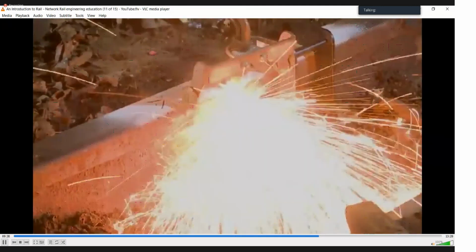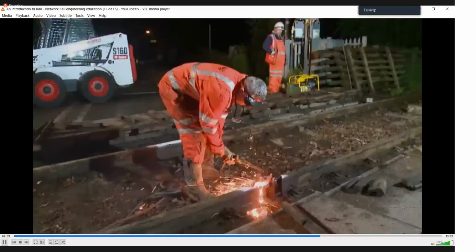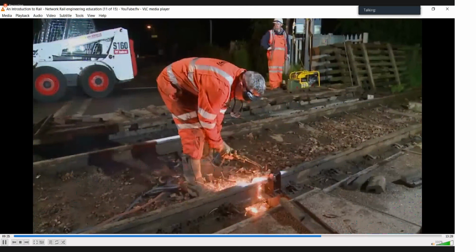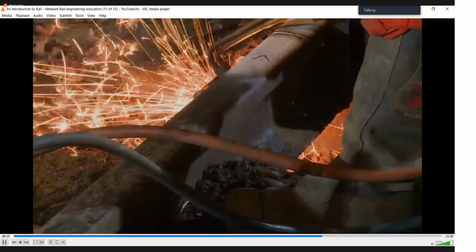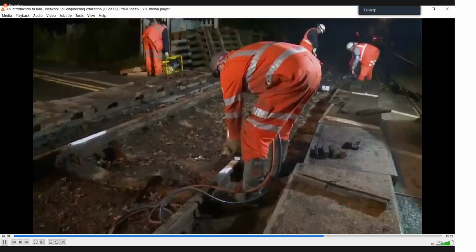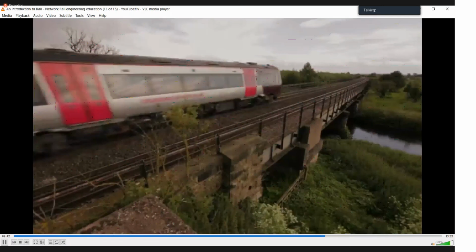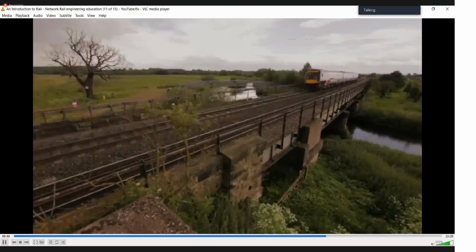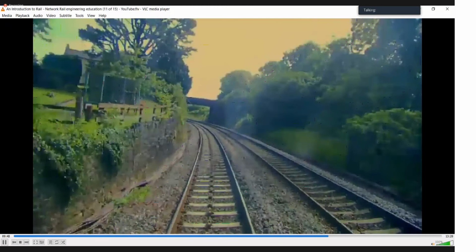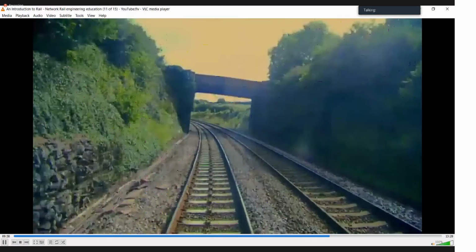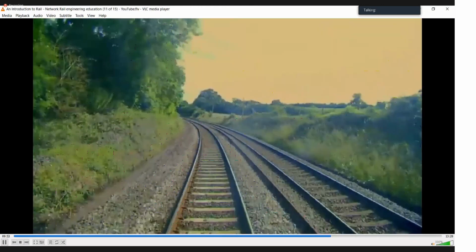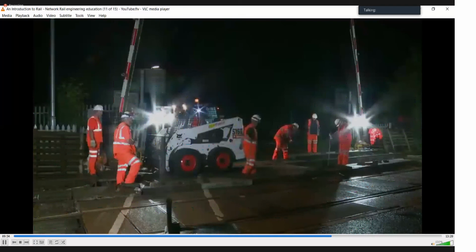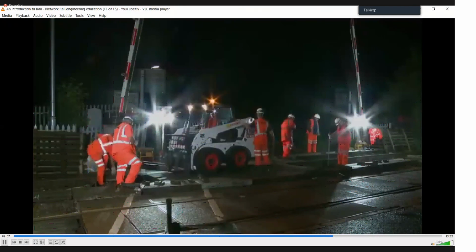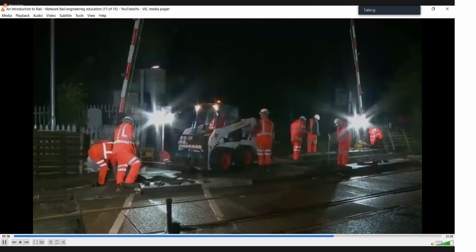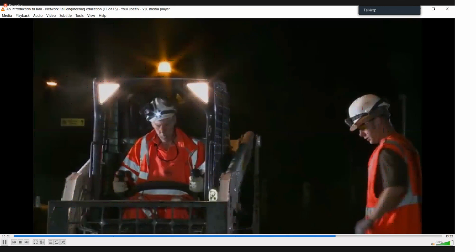Eventually, however, it will be necessary to replace the rail. The primary reasons are the number or severity of defects, wear or corrosion. Some rail can last up to 40 years if on a straight piece of track, but on the curves of a high-speed line, or where the rail is affected by road salting, the lifespan can be reduced to less than a year. Typically, if a relatively short section of rail needs to be replaced, this will be done at night to minimize the disruption to traffic.